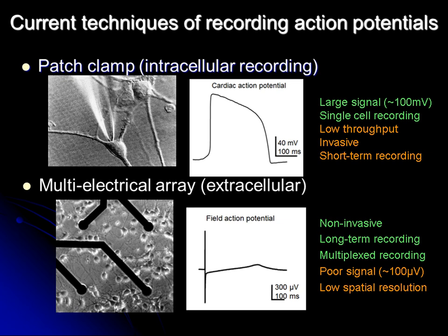On the other hand, extracellular recording is non-invasive. We can record the same cell for months. Another big advantage is you can record many cells at the same time, such as hundreds of cells. However, despite that, the multi-electrode array system has been around for like 30 years, and very few neuroscience labs actually use this technique. That's a key disadvantage. It has a very poor signal. We're talking about 100 microvolts compared with 100 millivolts for intracellular recording.